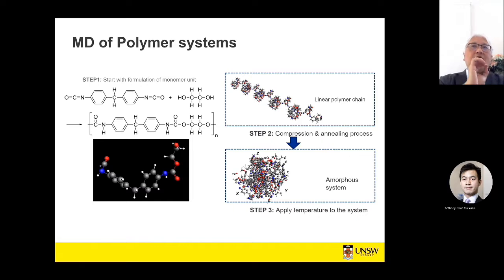And in order to do so, with polymers, an initial step is required, because in actual fact, the polymer is basically a chain of these linear molecules joining together. But to replicate the actual foam material, we need to carry out a compression annealing process so that it becomes an amorphous system that mimics the polymer matrix in the foam, okay? And this is done by applying a suitable temperature to carry out this process.